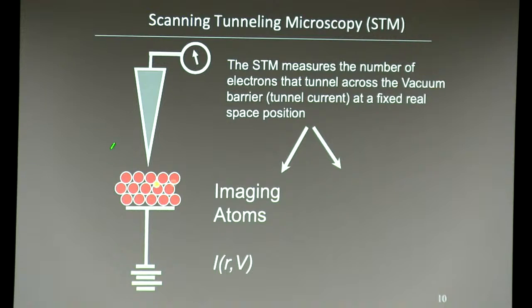We measure this tunnel current, and you can measure it as you change the voltage, as you change the tip sample distance, or as you raster the tip across the sample. Simplistically speaking, a measure of the tunnel current as a function of position gives you the topography.